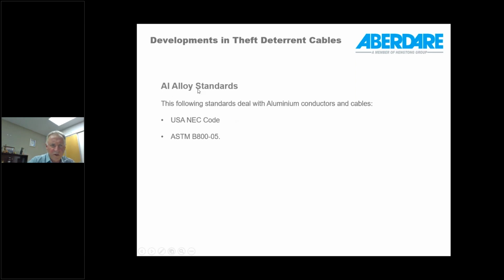So once again, the aluminium alloy standards are well documented in the ASTM standards, but the USA wiring code, so to speak, the NEC, also allows these small conductors to be used for wiring applications. And although the USA had very bad experiences in the earlier years with aluminium, it was with standard 1350 aluminium where creep caused major problems for them, and many fires were caused through the use of standard aluminium for these small sizes.